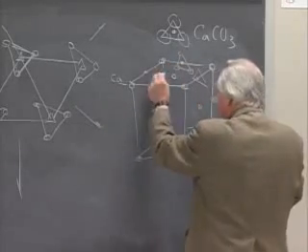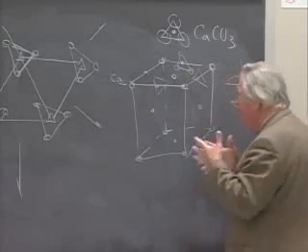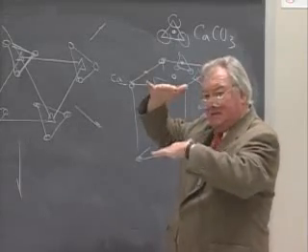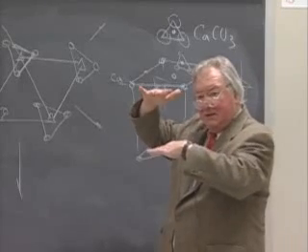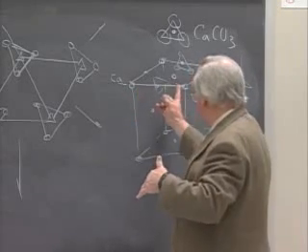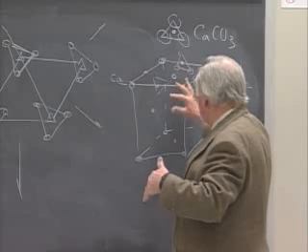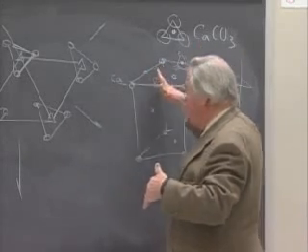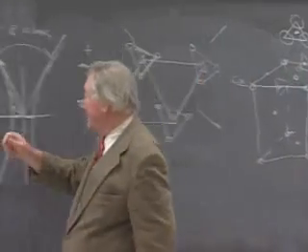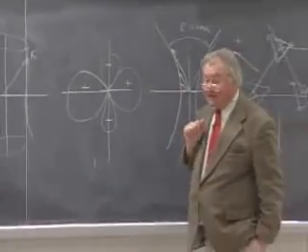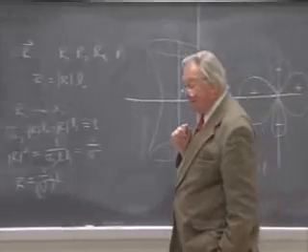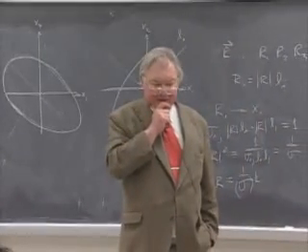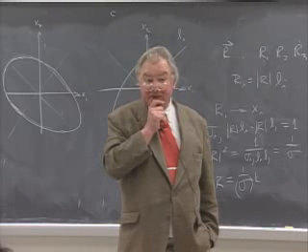Again, these tightly bonded little triangles don't do much as you increase temperature, but the bonding between the calcium and the triangles is rather weak. So again, you find that the structure expands in one direction so strongly that it contracts in the other direction. So calcium carbonate, the calcite form, also has the distinction of having a negative thermal expansion coefficient. We'll talk quite a bit about expansion coefficients as one example of a tensor property.